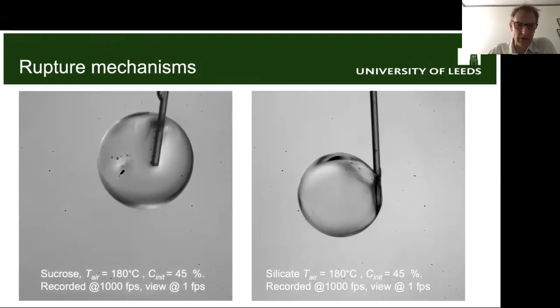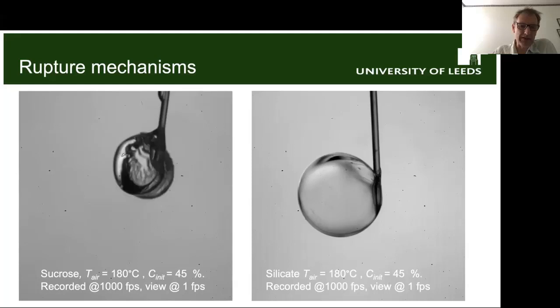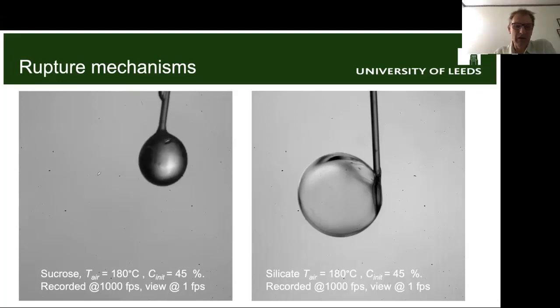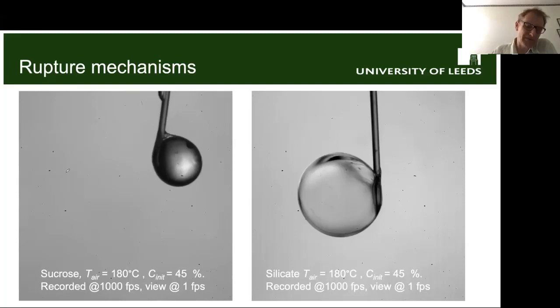hopefully if I press this, yeah, we go, an insight, if we're looking on this left screen, into what's happening when they puff. So this is actually a blown up balloon of sucrose, and that is the film rupturing. And then we get this little jet of liquid which comes out of the droplet. And gradually then this will re-inflate. And again, it will burst. Sometimes they spit out this little, what you might call a Worthington jet, which is where you have a film which contracts rapidly and forms this reflexive jet. And that's why you get, these are the liquid-like properties that were giving you this behavior.